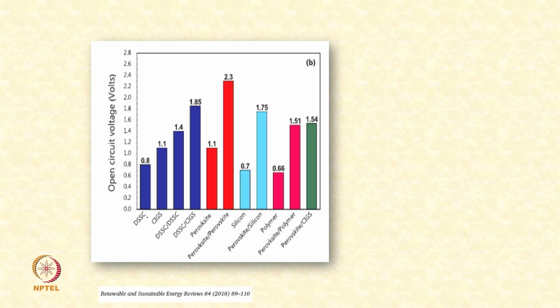So it is with dye sensitized solar cell, which typically has a VOC value of 0.8, and then if we have a dye sensitized and dye sensitized solar cell both, then we have a typical VOC of 1.4. So only dye sensitized is 0.8, and if we have DSSC and CIGS solar cell, it is 1.85, and if we have two perovskite solar cells, the red one, which shows very high VOC. So far we have not seen in our discussion that one can also have a VOC of about 2.3 volt.